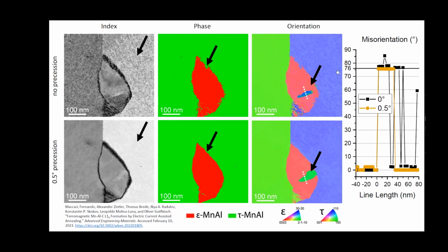And as a secondary piece of information that we can extract from this data set, I also drew some line profiles across that even smaller inclusion in the tau phase grain. And this is something I did not explain yet, but it's a solid state phase transformation, the transformation between the epsilon and tau phase. And during this ordering step and shear step in the phase transformation, there's a high probability of twins being formed in the tau phase. And for these twins, theory predicts that there's a misorientation angle of 76 degrees between the two twins in the tau phase. And if we draw a line profile around that dotted line that you can see here, we actually do see a misorientation of exactly 76 degrees, which is also quite important to see, because this is, as I said, a current annealed sample right at the verge of being transformed completely from the epsilon to the tau phase.